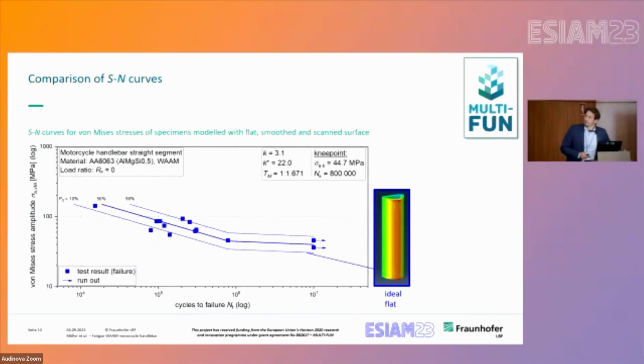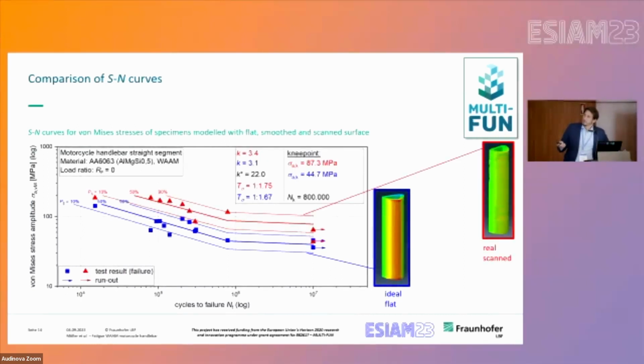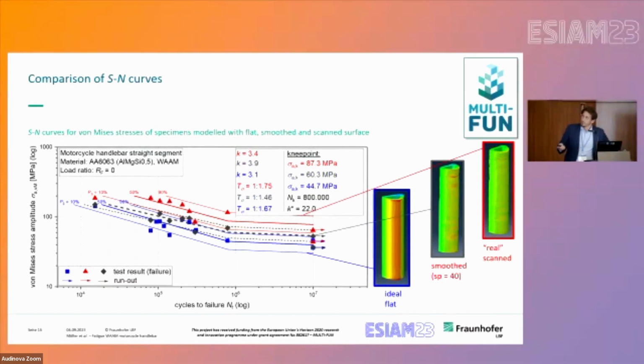And from this, the question is, if we apply this maximum stress to the SN curve, so that we have now, instead of just the moment, the von Mises stress amplitude versus cycles to failure as a basis. The flat specimen is the reference, and compared to this, the real scanned geometry gives us an idea of the stress concentration of the fatigue-pronounced notch. And compared to this, in between, is now a little bit hard to see, there is the smoothened one for sure, where we have a lower stress compared to the real scanned geometry.